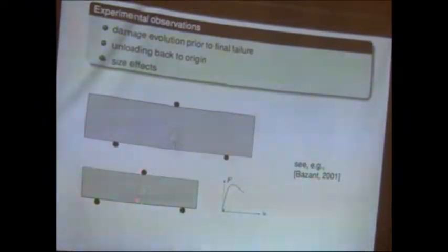So if we have two specimens of different sizes under the same, let's say, nominal load regarding the fracture zone, a smaller specimen will fail first because in relation to the specimen size the damage zone is so-called bigger, which is not, because in both cases the damage zone is actually more or less the same, but for the small specimen, the damage zone will reach the surface, so to say, faster.